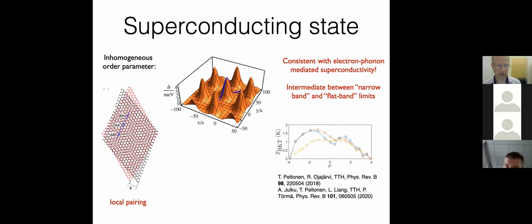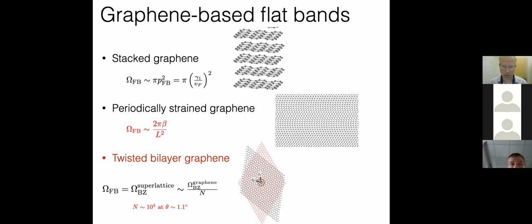Another thing we can find out is that the size of the measured BKT temperature points out that this is in a regime intermediate between the narrow band and flat band limits. So in order to understand any mean field property, any measurable property of the system, you cannot expand around the Fermi surface, but actually have to take into account the entire flat band for this property. Okay, so this is my summary slide.